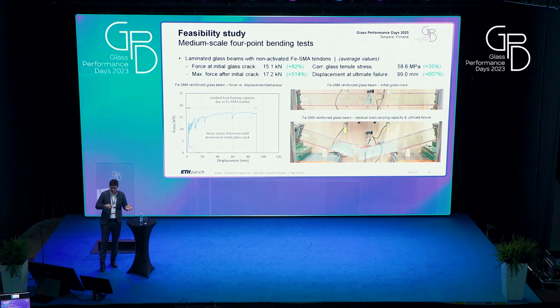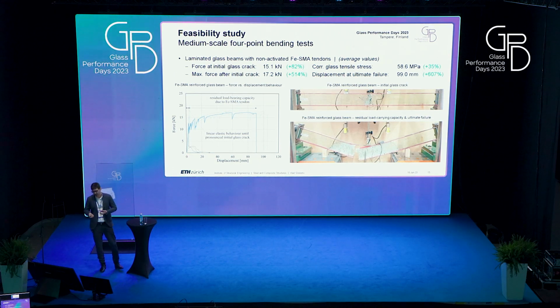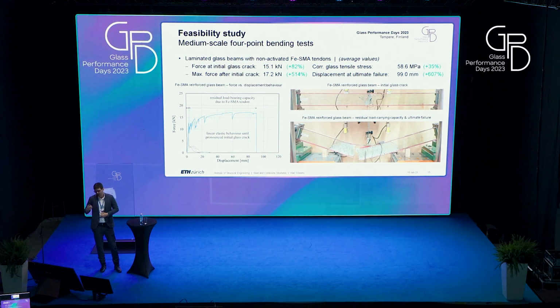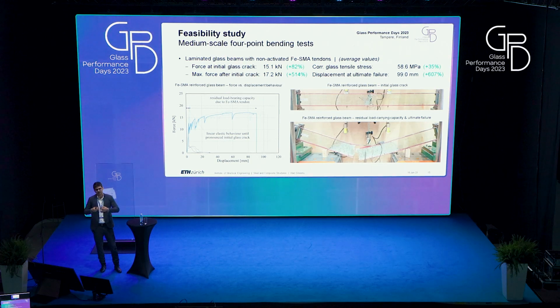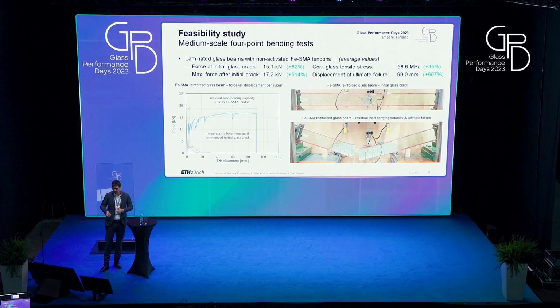And also after the primary crack, we were able to carry quite high loads for a long amount of time. For these beams, just with tendons that were not activated, we had tendon rupture at the end.